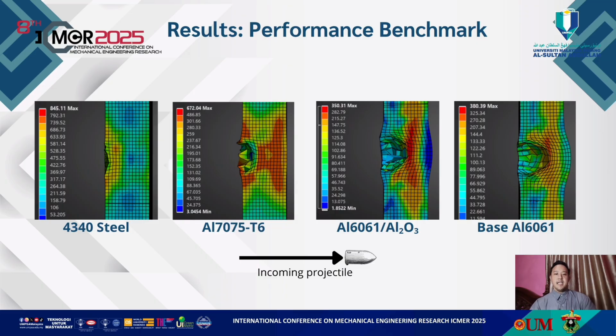The stress distribution in the aluminum 6061 with the 15% aluminum oxide reinforcement highlights its combination of brittle and ductile behavior. A concentrated high-stress region forms just beneath the impact point, indicating the initial resistance offered by the hard aluminum oxide particles. However, when compared to the base metal, aluminum 6061, which demonstrated a typical ductile response, the stress is spread wider over a larger area. It is not capable of resisting impact forces locally.